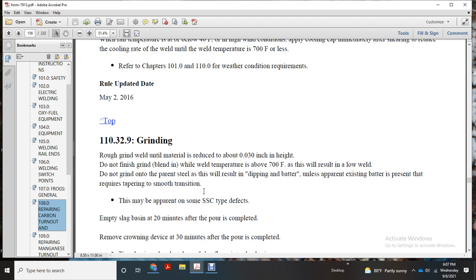Rough grind the weld until material is reduced to about 30,000ths of an inch in height. Do not finish grind or blend the weld if the temperature is above 700 degrees Fahrenheit, as it can result in a low weld. Do not grind into the parent steel, which would result in a dip in the rail, unless the apparent existing batter is present. This requires tapering and a smooth transition. This may appear on some SSC type defects.